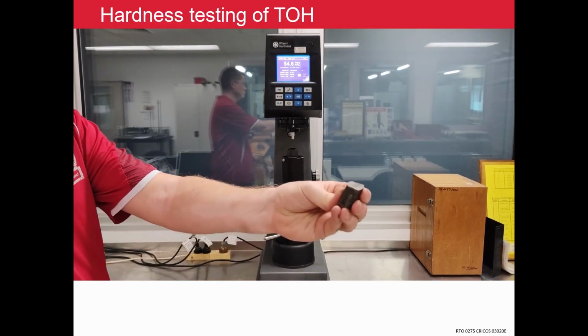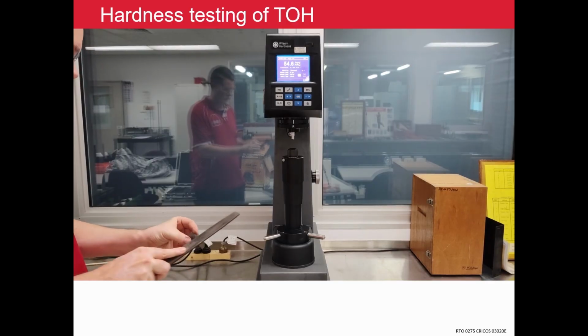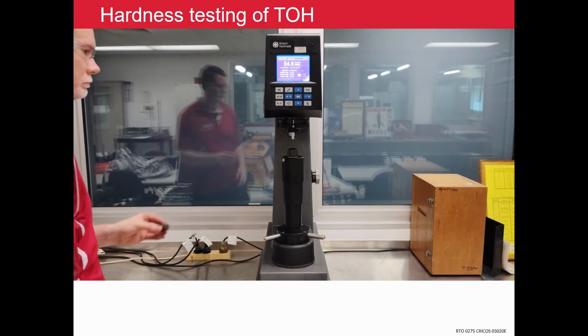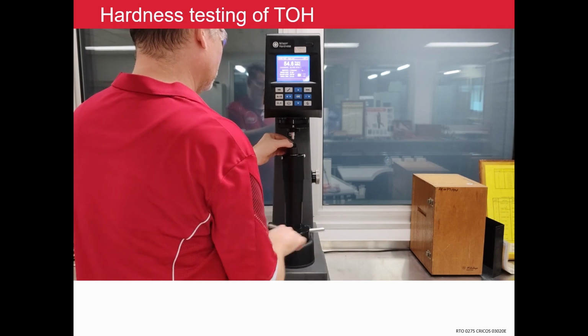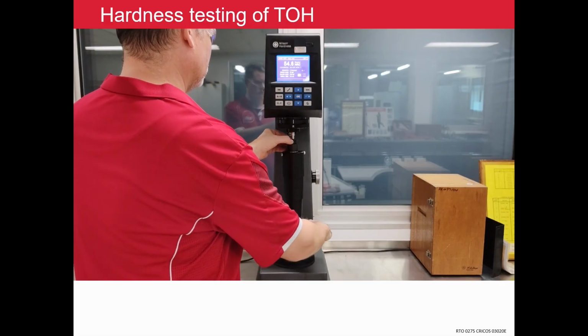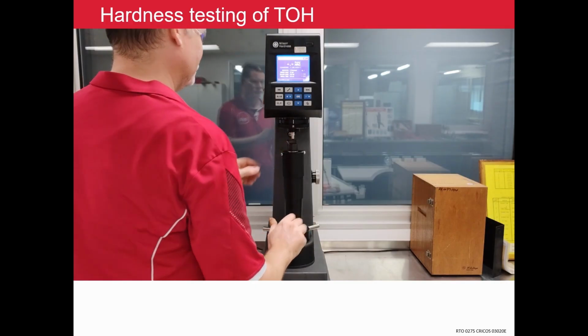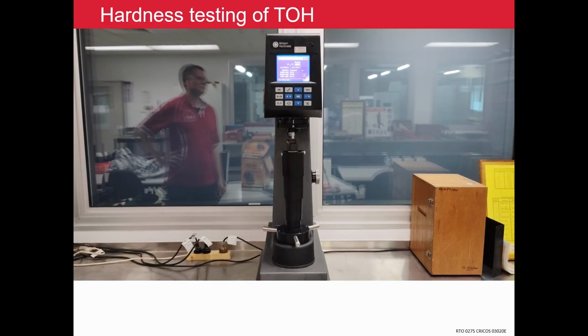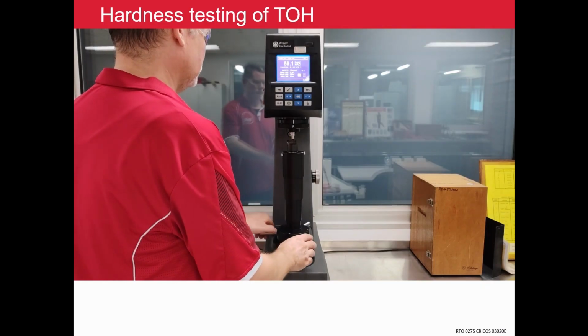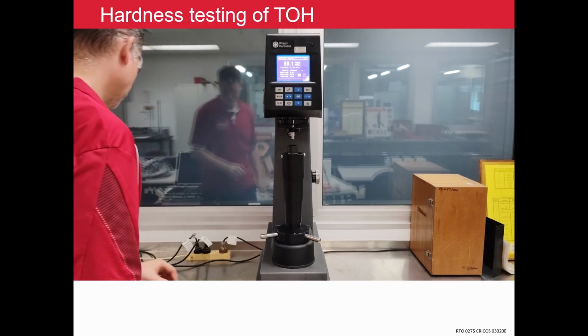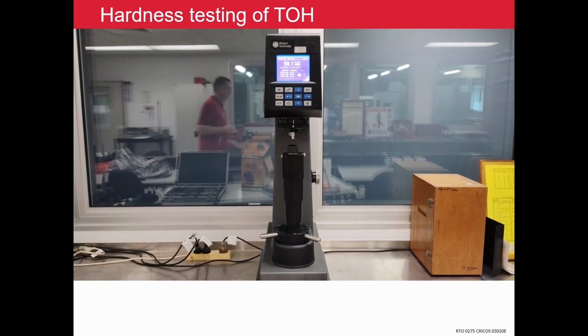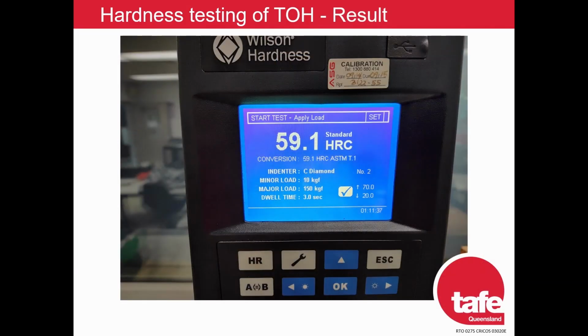The TOH sample is prepared and the hardness test is carried out. Any surface scale is removed using the file. The TOH registers a hardness of 59.1 on the Rockwell C scale. This high hardness value confirms martensitic transformation and suitability for tool applications requiring wear resistance.